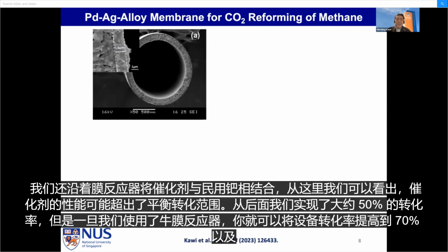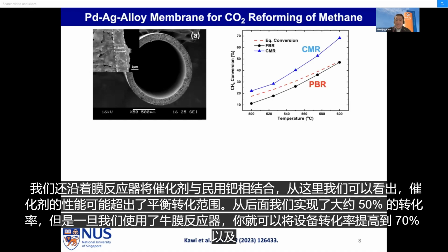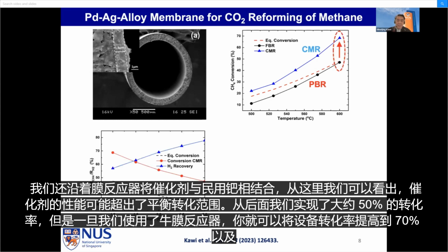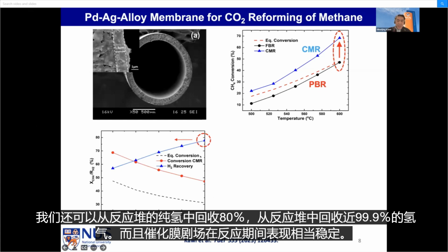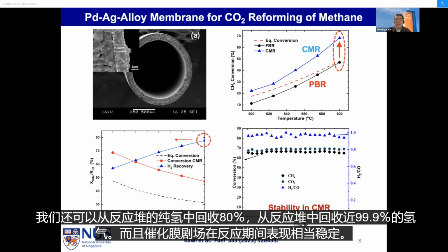We also integrate our catalyst with the palladium-silver alloy membrane reactors. You can see from here that the performance of the catalyst can go beyond the equilibrium conversions. From the packed bed, we achieve about 50% conversion, but once you use the catalytic membrane reactor, it can increase beyond the equilibrium conversion to 70% conversion. We can also achieve 80% recovery of pure hydrogen, almost 99.9% hydrogen from the reactor. And the catalytic membrane reactor performs quite stably during the reactions.